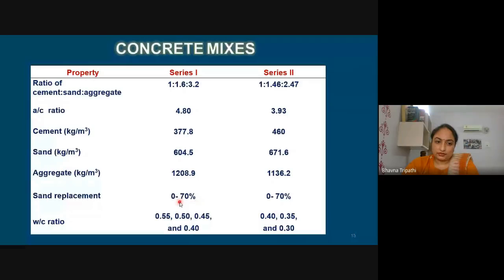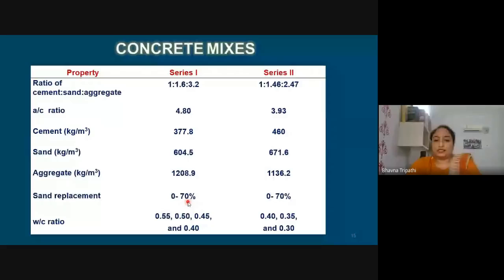Sand was replaced with ISF slag from 0 to 70% in increments of 10%. And why we had limited it to 70%, we did not go to 100%, because after 70%, it was very difficult to prepare the concrete mix practically. Concrete beyond 70% replacement showed the deficiency of paste, and the reason for this is lack of fines.